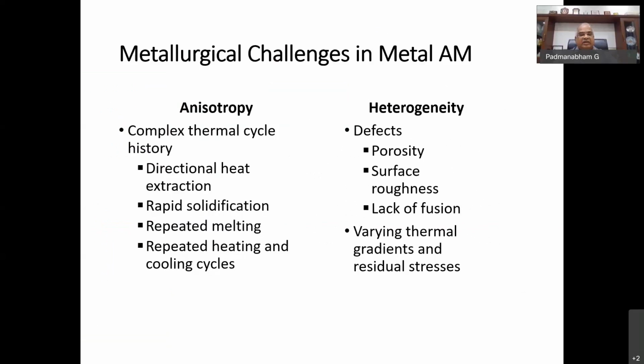And then the layers that you have built in the past, as you are building the Z planes, those bottom layers are experiencing repeated heating cycles and cooling cycles. Another thing is that different zones experience different gradients and solidification rates. And then the solidification morphology changes, sometimes even from cellular to dendritic to equiaxed grains. So all that will reflect in the mechanical properties and the other heterogeneities that we create.